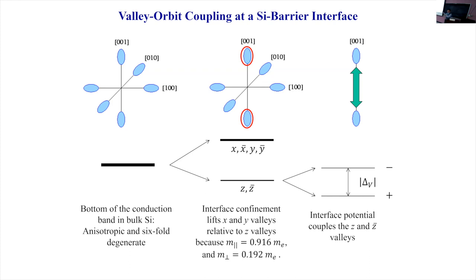If you think of the valley-orbit coupling as real, then you have the Z plus Z bar as the ground valley, and Z minus Z bar as the excited valley, with a splitting that depends on the strength of that scattering, right? Well, unfortunately, that coupling actually is not real. It's generally complex. So the superposition actually depends on the phase of that valley-orbit coupling.